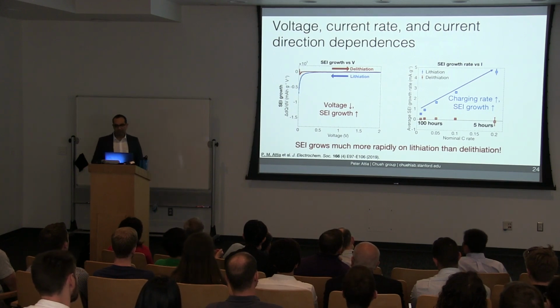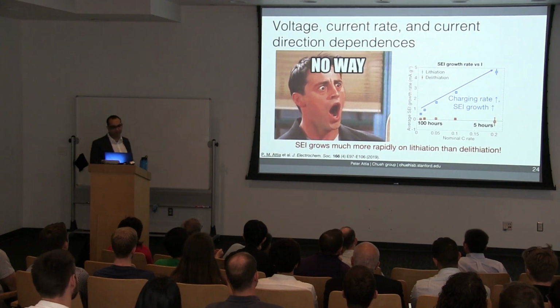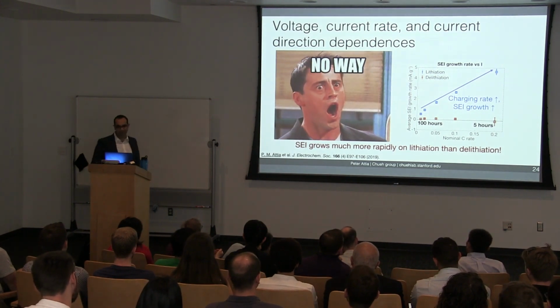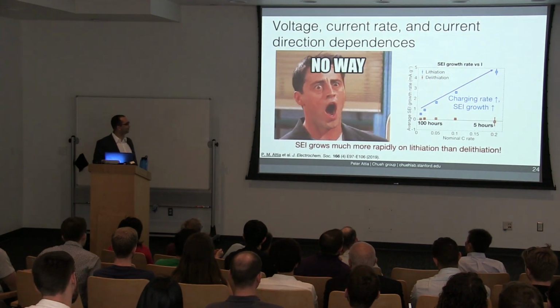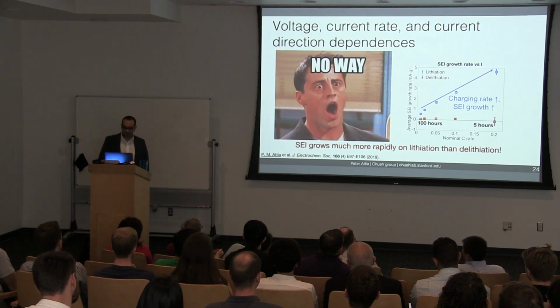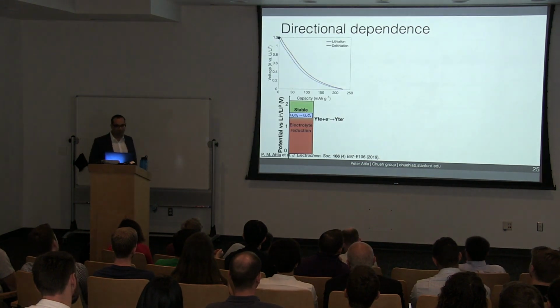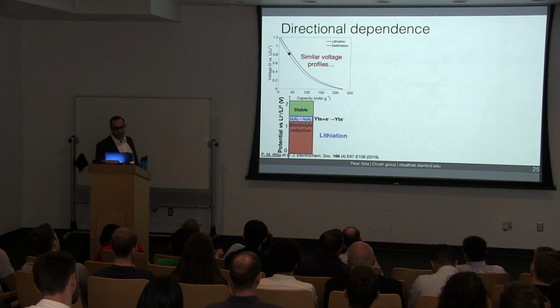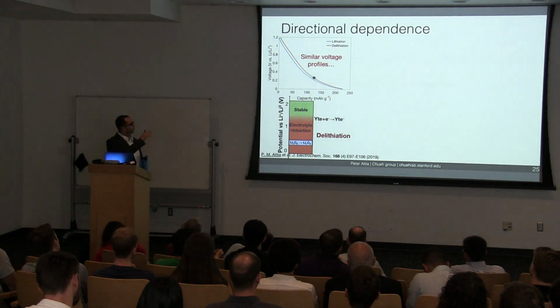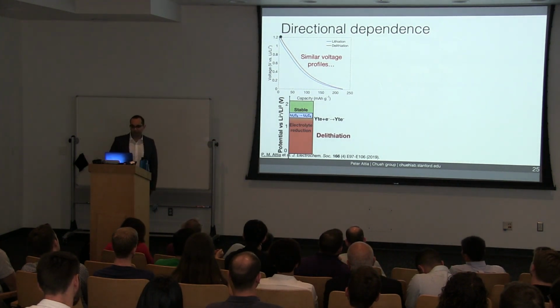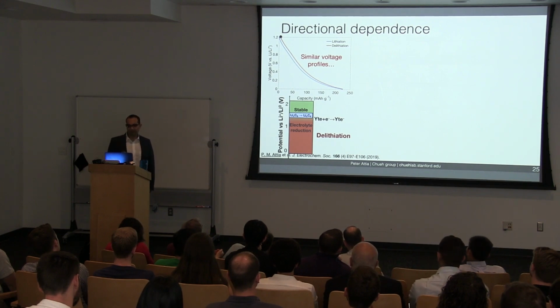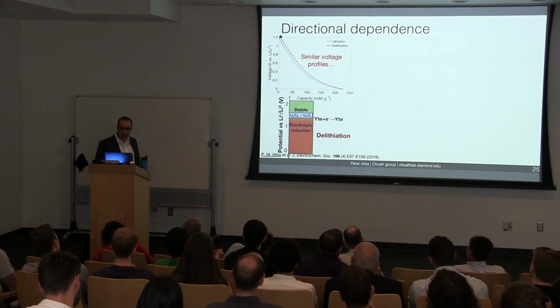I really want to emphasize how striking this is. The fact that SEI grows so much more in lithiation relative to delithiation is probably the most surprising result from the PhD. Let's explore this directional dependence a bit more. During a single cycle, the voltage during lithiation and delithiation is similar. The electrode spends a similar amount of time below the stability window of the electrolyte. So we'd expect similar amounts of SEI in both directions.